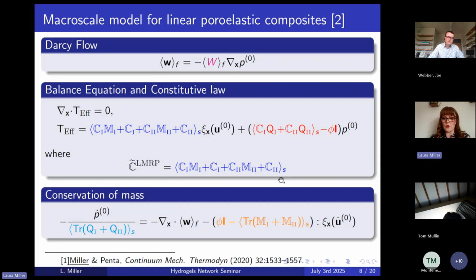So we then just want to present our final macroscale model, which is a system of PDEs, as I mentioned, and our first equation is for the Darcy's flow that we find for the fluid flowing in the pores. So this W, lowercase w, we find here is just our relative fluid solid velocity that we have defined to make determining the equations a little bit easier. And we have this pink coefficient here, which is our effective hydraulic conductivity tensor. So that is remembering the underlying pore geometries that are at the microscale, even though we're now in a macroscale PDE. And that W is to be obtained via solving some of those microscale cell problems that I mentioned. And that is how it's able to remember the pore geometries and vessel geometries that we're going to be seeing in the underlying material.